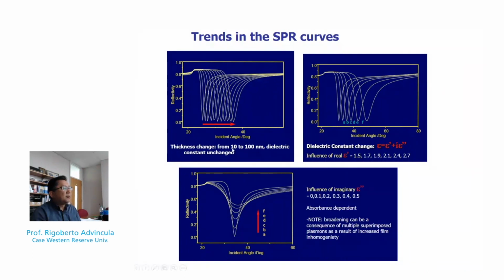Let's say the dielectric medium shifts from 10 to 100 nanometer. You can see almost a linear shift on the reflectivity curve towards higher angles as you have thicker films. Or if you have a dielectric constant change, as a function of the real part of the dielectric constant, sometimes we call it refractive index. That means if you change that value from 1.5 to 2.7, that value also shifts. So this is one rule with the SPR curve: you either have to fix the thickness or fix the dielectric media, but if you start changing both, then it's hard to model or account for the influence of one over the other.